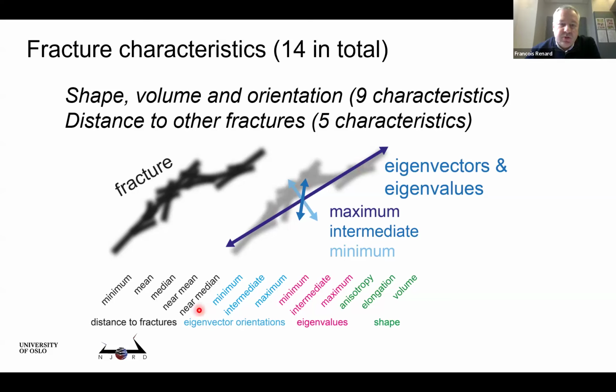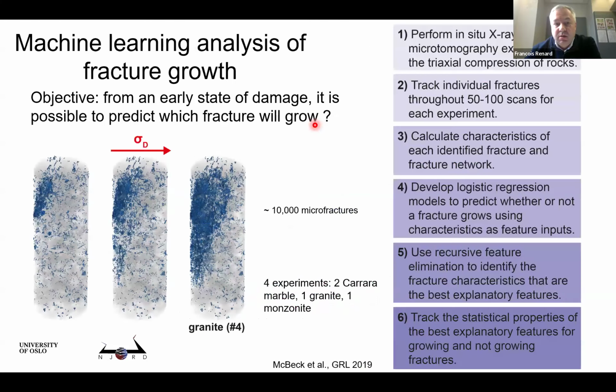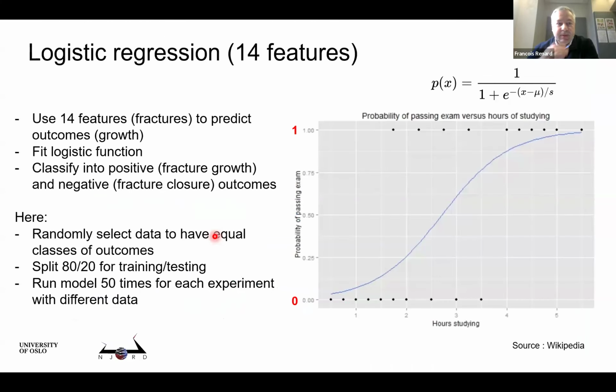And then we look also at the distance between fractures. So for each fracture, we have 9 plus 5, 14 characteristics. So we have a big Excel spreadsheet where for each fracture, we have all these 14 parameters. And for each fracture, we know if the fracture is growing or not. And then we fit logistic regression.